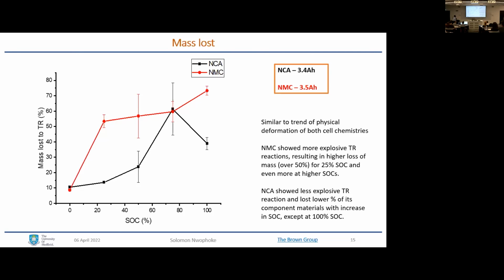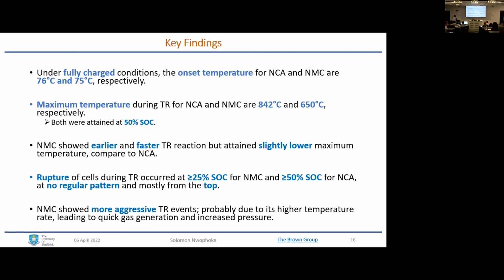So you can observe from here that NMC showed more explosive thermal runaway reaction, resulting in higher loss of mass, from as low as 25% up to about 50%, while the NCA showed lower explosive reaction. Then that brings us to the last slide, which is the key findings.